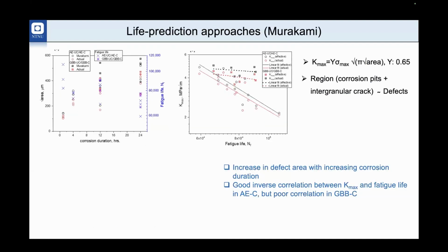Now we also tried to delve a bit into life prediction using the Murakami approach. And as you know, using the Murakami approach, we basically consider some defects. Here there are no defects in terms of porosities or inhomogeneity or inclusions, but we consider the corrosion pits and the intergranular cracks as defects. For the effective area, what we did is make a contour considering just those regions, and in this way we measure the defect size.